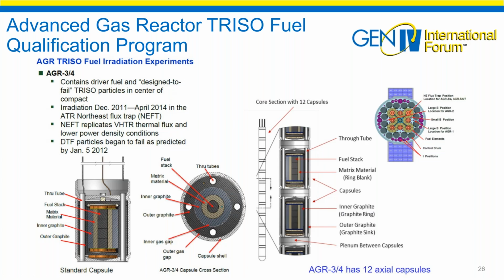Why would you put it in the very center? Well, the NRC said, if you don't know where you put them, then you don't know the distance a fission product went. So you don't know anything about the diffusion of the fission products. Well, our folks at Oak Ridge were very clever. They used basically a very thin straw, and carefully parked the 20 particles with a little bit of matrix, and they just put it up through the metal, and then they removed it with the other particles around it and compacted it, and then they did radiographs. So we know where the particles are in these designed-to-fail particles.